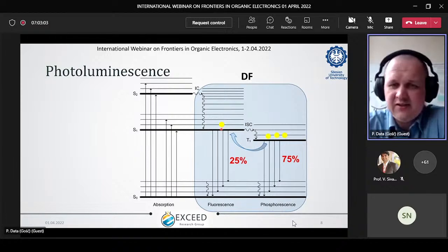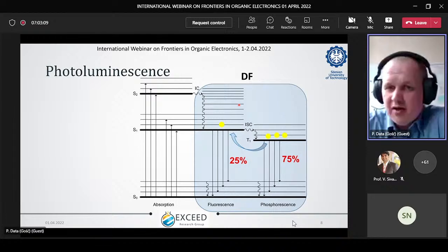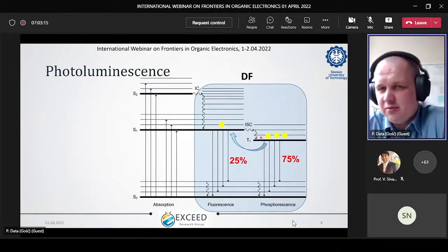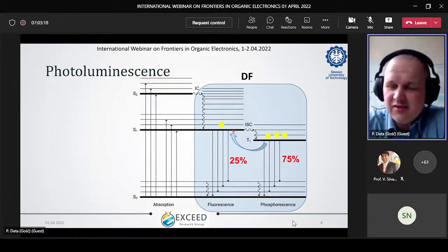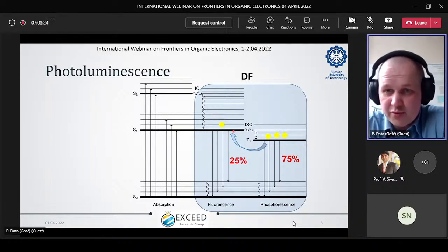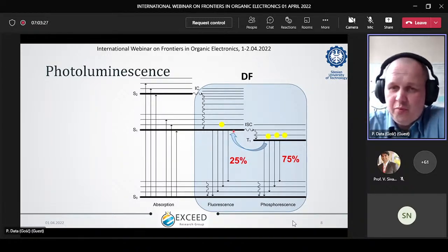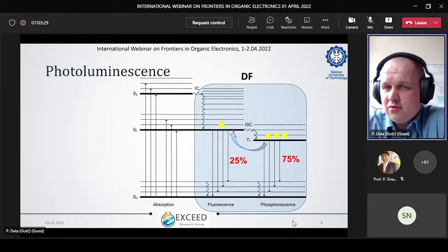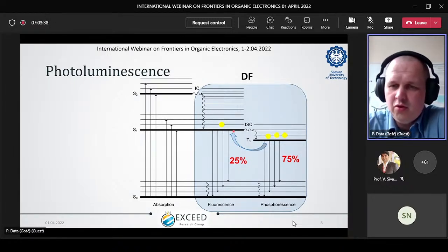We are pushing it to the singlet state, the singlet state where we have fluorescence emission. But because again we need to have a spin flip and we need to go firstly through intersystem crossing and then reverse intersystem crossing, it takes time, and that's why we don't have normal fluorescence but the delayed fluorescence process. Nevertheless, in both cases, phosphorescence emitters or delayed fluorescence emitters, we can harvest up to 100% of our excited states. And that's our goal in the new OLED emitters, to use delayed fluorescence and get as high efficiency as possible.